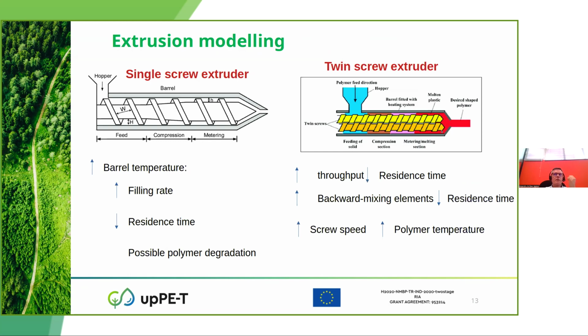The temperature of the blend will differ from the barrel temperature due to mechanical energy transfer from the screws to the molten material. In single screw hot melt extrusion, temperature mainly affects the flow rate, as a polymer's flow properties are proportional to its viscosity. When you increase the barrel temperature in single screw extruders, you increase the filling rate, but decrease the residence time of the product in the barrel.